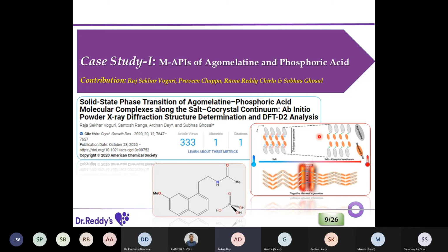And what I would highlight here is, if you have advanced characterization, a very robust computational protocol, combined with very strong crystallographic or chemical crystallographic analysis, if you can connect all these things, at the end of the day you can visualize or propose some mechanism of phase transitions, especially the solid state phase transitions we have observed here. So it is along the salt co-crystal continuum. That's how we are extracting the information and moving towards understanding the phase transition in a mechanistic way, which hopefully gives more levers to control the material in scale up and process.